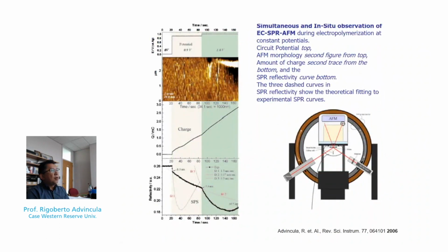And just to give you another window, this one, we have a potentiostatic deposition. So what we did is we ramp up the potential to about 0.8 volt, 0.9 volt, and then we stabilize it further. We did the AFM single line or single point rastering, showing again the change in morphology as you shift to a higher potential. Not as big as the cyclic voltammetry experiment, but nevertheless discernible. And then this charge as we inject the electrons at a constant potential. And then of course the change in the dielectric media that was monitored using SPR.